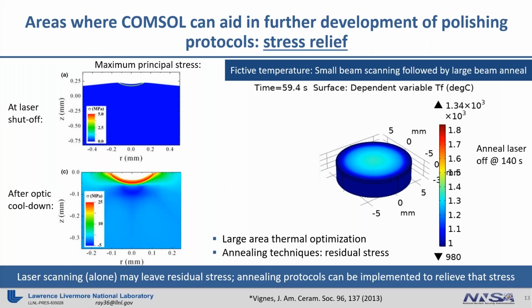And for some applications, that could be advantageous. But for most applications, you're going to want to avoid that. And I should mention that in the earlier mitigation processes, I mentioned the micro-shaping of fused silica to basically remove damaged area. In the first generation processes, residual stress was not taken into account, and those optics actually failed. So it's very important. And from the fictive temperature, you can actually work your way back out and get the residual stress. So that is an area where, moving forward, COMSOL can further aid in narrowing down the parameter space.